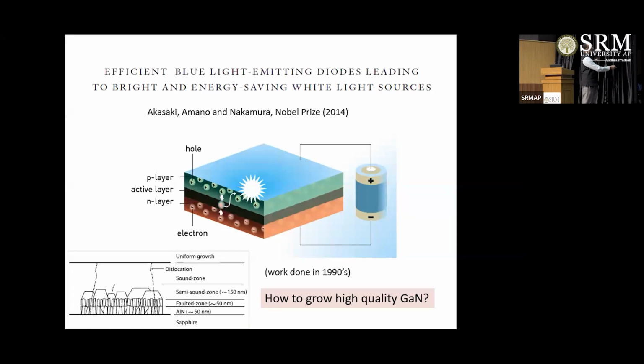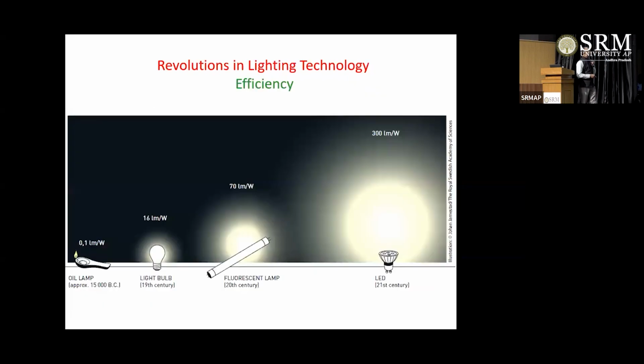But the Nobel Prize work was done in 1990s, and the Nobel Prize was given in 2014. And the reason for it is, even if gallium nitride has been known for decades or even half a century, the ability to grow it in a pure form was missing. The main achievement of this trio was to grow it such that only the bottom part of this film is defective and this top part of the film is very pure, with very low defect density. And if you can grow gallium nitride with this purity, then you can make light emitting diodes out of it. So this is the game changer.